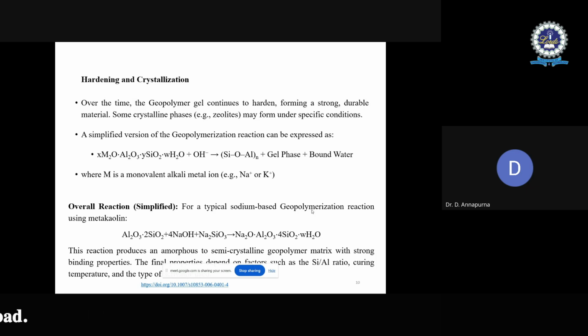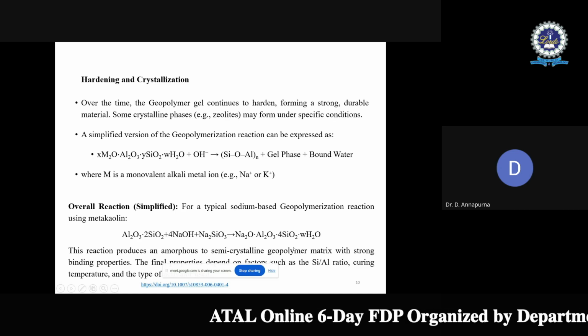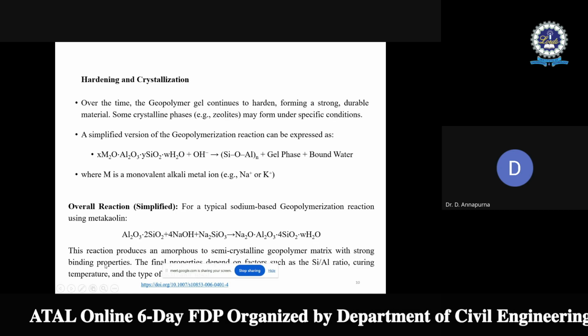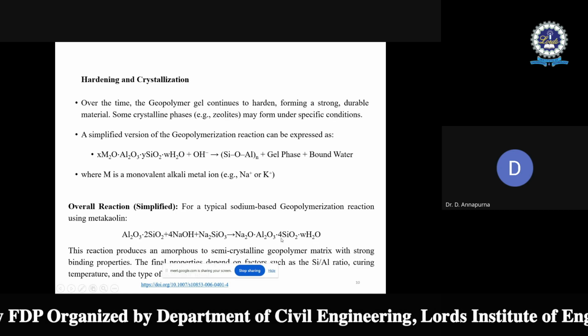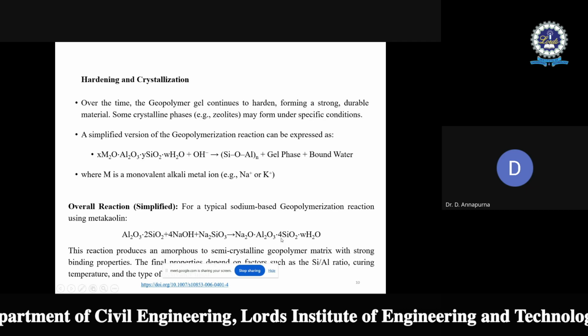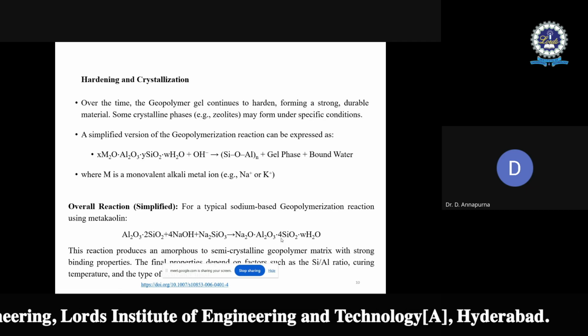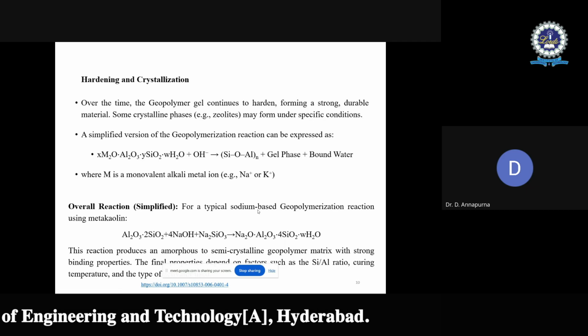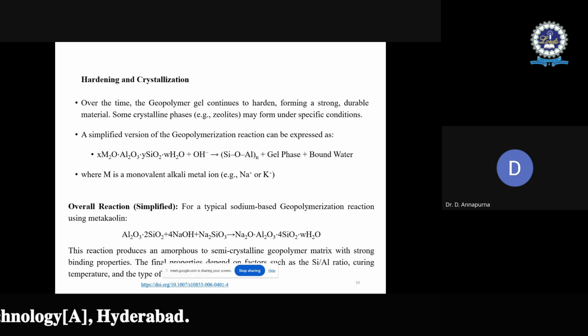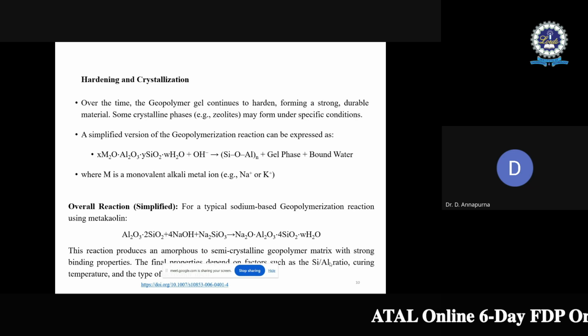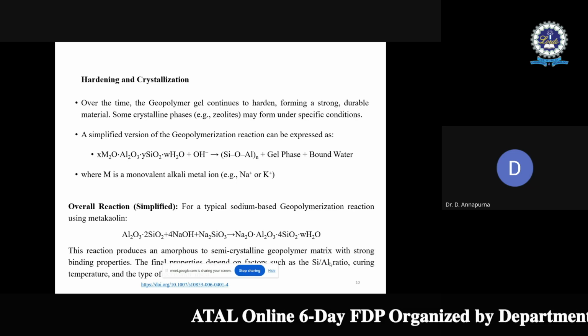N-A-S-H gel is the geopolymer product which produces an amorphous to semi-crystalline geopolymer matrix with strong binding properties. So this N-A-S-H will have strong binding properties and it is going to give strength to concrete. This N-A-S-H gel is going to form when the silica by alumina ratio in the formed geopolymer is between 1.5 to 2.